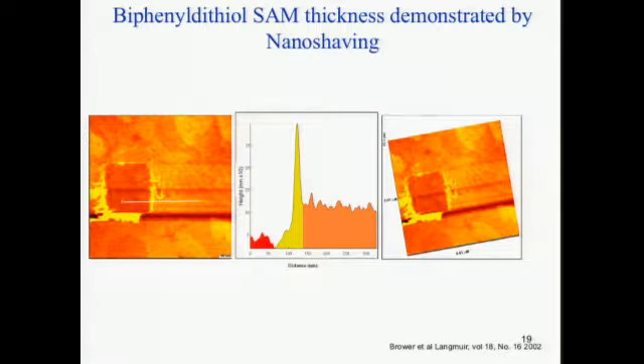At the time, nanoshaving was kind of a newfangled thing. If you come in with a monolayer on a gold surface and you have an AFM tip and you apply the correct amount of force, you can actually shave away some of the molecules, and then you can go back and with your cursor look at the difference in height between the hole that you made and the monolayer on the other side.